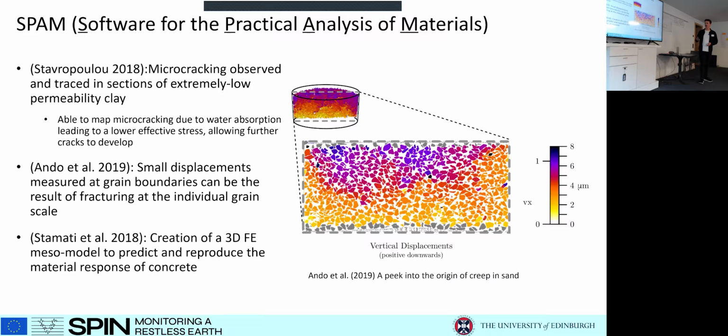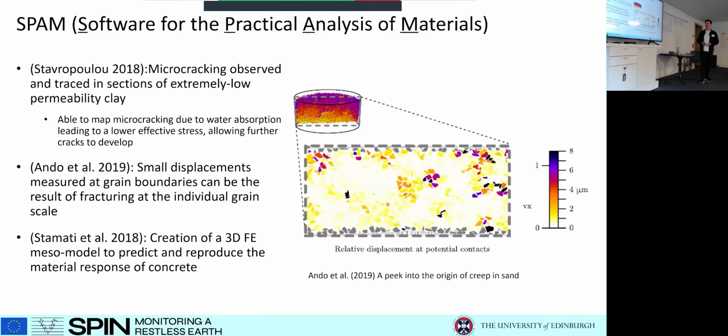The next one was done by Edward, who developed the project, and he looked at small displacements measured at grain boundaries and how cracks develop, and determined that small displacements at these grain boundaries are actually the result of fracturing at just an individual grain scale, which I thought was really interesting.